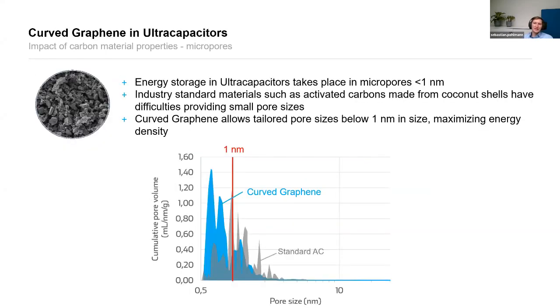So what does curved graphene look like? What we realize is that energy storage in ultracapacitors or supercapacitors takes place in very small micropores, below 1 nanometer, which is very good for the common industry electrolytes. The electrolyte that we were using in the other study was a slightly different electrolyte. If you have standard materials like activated carbons made from coconut shells, those normally provide a mixture of pore sizes. Here in gray you see the standard activated carbon with the different pore sizes that you find. They always try to get a pore size of around 1 nanometer in these activated carbons as well.